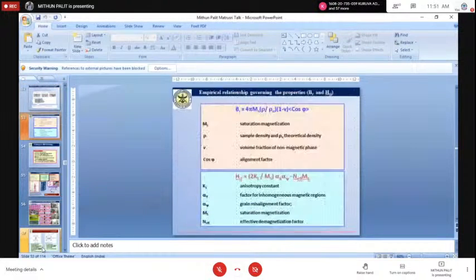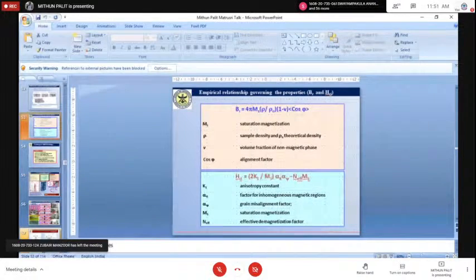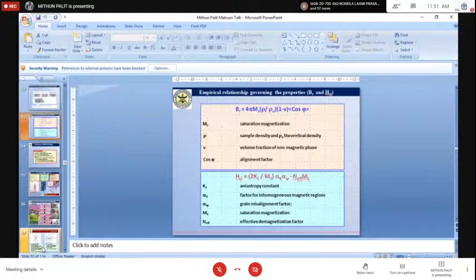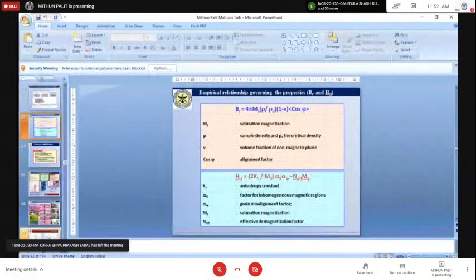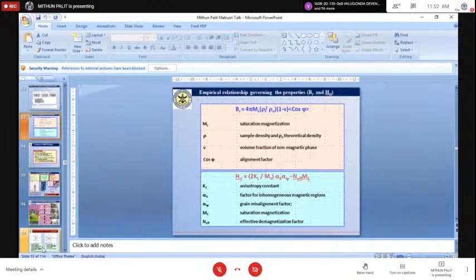And this is the formula that computes the coercivity and the BR, that is the remanence, of this permanent magnet material. You can see in the case of the remanence, a cos phi term appears. This cos phi term says the orientation, in which crystallographic direction the magnet is oriented. So an oriented material is required, and also the density, shown by rho, and the volume fraction of the other non-magnetic phases. Coercivity also depends on several such microstructural parameters. So tailor making the microstructure and grain orientation, all these things are very important for processing of permanent magnets.